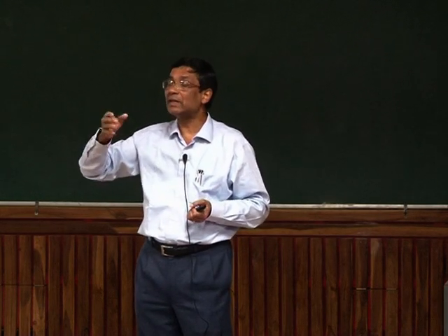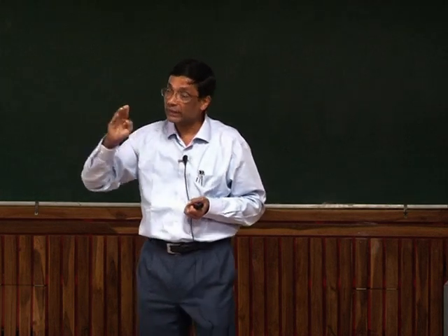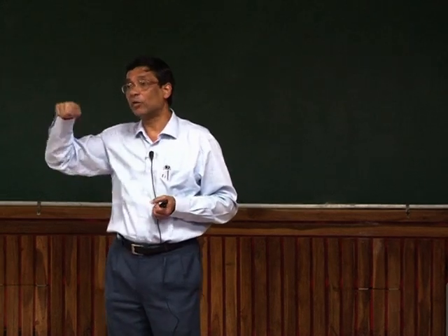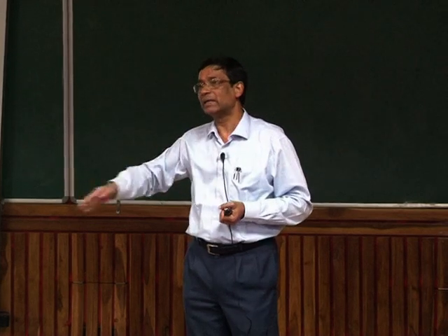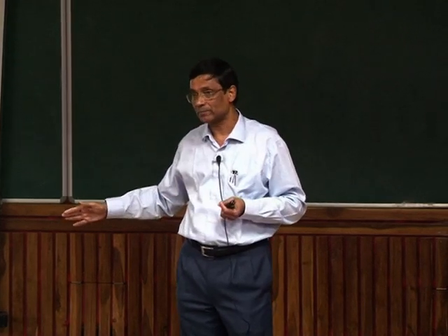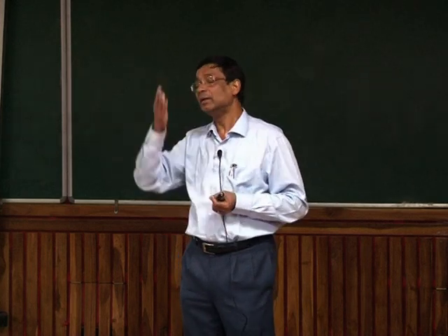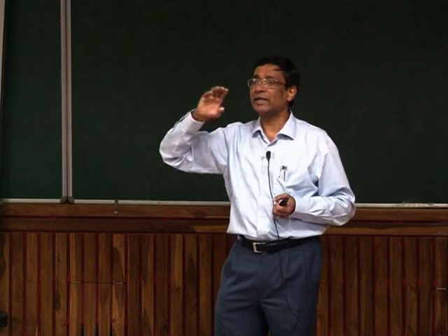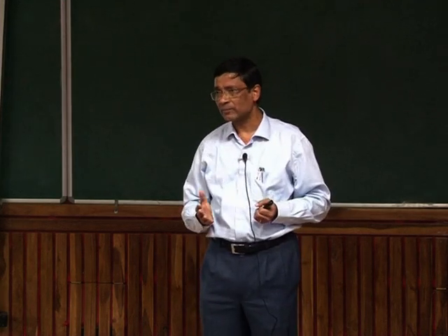Approximately lambda amount of thickness I can see. When d becomes larger than lambda, the probability, e to the power minus d over lambda, cuts down very quickly. e to the power minus 1 is on the order of 37%, and it decays exponentially further out. So let's think that I can get information up to 3 lambda, approximately speaking.